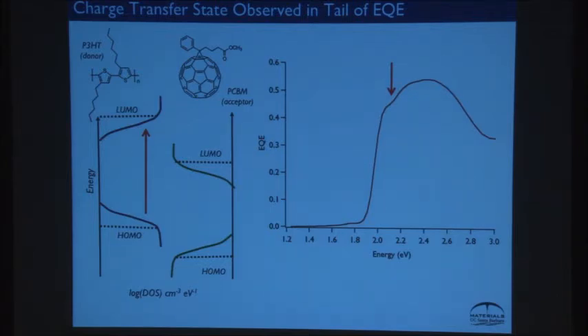It generates a lot of charge that you can pull out. There's an excitation for the fullerene. If you made a neat fullerene film, you'd say the excitation is here. It's a weak absorber due to symmetry. It's about here, and you actually still see some charge there.